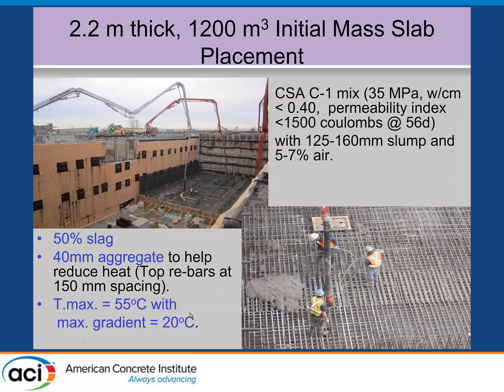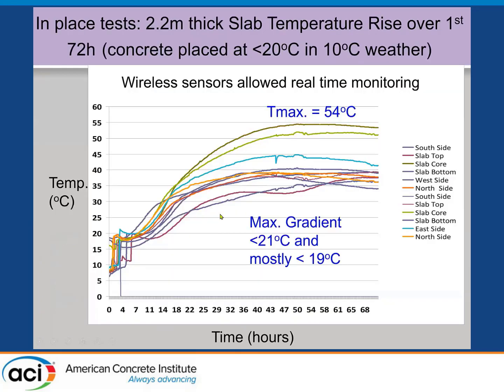We had a spec of 55 degree max and 20 degree differential. And they used wireless sensors. They instrumented this slab, and they met this thing. This is over the first 3 days. It maxed out at 54 degrees. The maximum gradient at one place was 21, but almost everything met the 20 degrees.